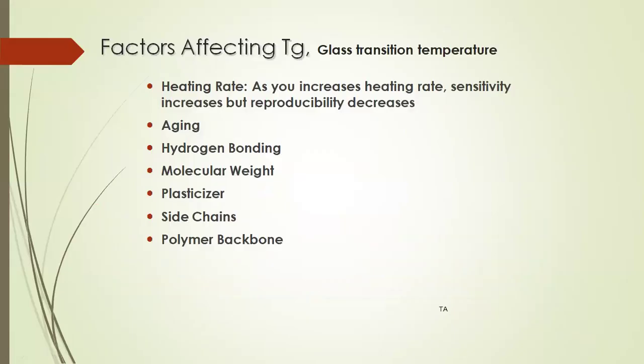So in DSC, we are measuring glass transition temperature and melting temperature mainly. And crystallization kinetics or crystallization temperature and delta Hc will be automatically measured, because if you cool the material, you will get delta Hc. So what are the factors that affect your glass transition temperature, TG? Heating rate, aging, hydrogen bonding, molecular weight of the sample, plasticizers, side chains, and polymer backbone. In research, a student can correlate: if you are increasing the molecular weight of your sample, you can find out the TG, find out the TM, and you can find out whether your molecular weight is really increasing or not.